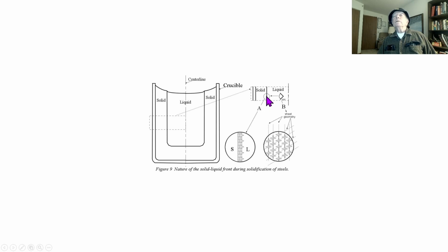Well, it is in pure metals, pure iron, pure tin, but it is not in virtually all alloys. It consists of arrays of small needle-shaped regions that look like trees and are named after the Greek word for trees, dendrites. So these dendrites are growing in arrays. If you look at the face from the solidified front, solid interface, from this direction, that's what it looks like. You can see the individual dendrites, and in each individual grain, these guys are all lined up. Now, what I want you to think about is that you have alternating arrays of dendrites and interdendritic regions.